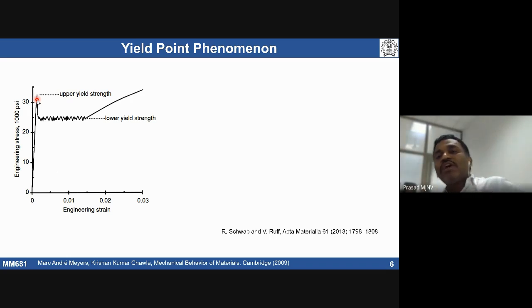That means basically locking - dislocations can be locked by solute atoms. During elastic deformation, even at room temperature, you have some interaction. When you deform them at that rate, we do see some interaction between dislocations and solute atoms. So there is an interaction.